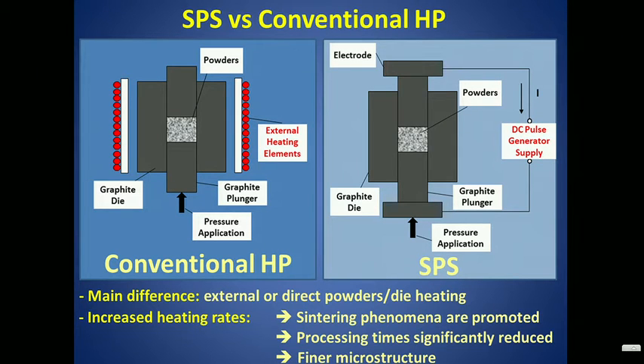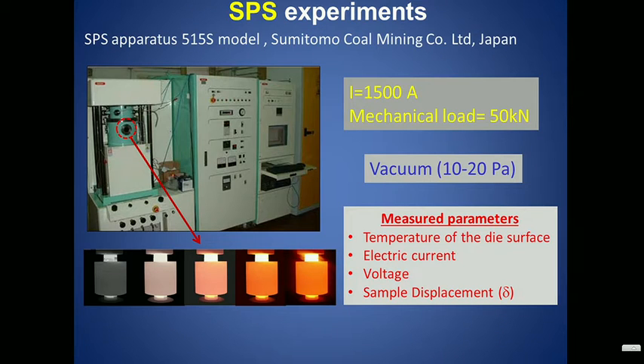hot pressing technique and the SPS, if you take a look at these two pictures, you have external heating in one case, and direct powder and die heating in the other. So at the very end, with the SPS, sintering phenomena are promoted. You have a much shorter processing time and a finer microstructure. We have been showing results that we have been obtaining with this machine. As far as you know, this is the very first machine that came to Italy, in 2003. At this point, there are only 3 machines in Italy of this type. 2 of them are in Cagliari. There are about 20 machines of this type all over Europe.